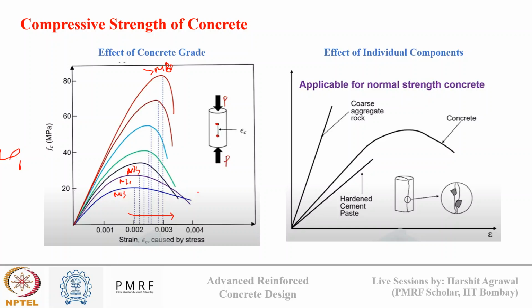Thus lower grade concrete deforms more till complete failure, and thus is more ductile, while higher grade concrete shows brittle failure. So this is the effect of concrete grade on the stress versus strain profile when concrete is subjected to compression.